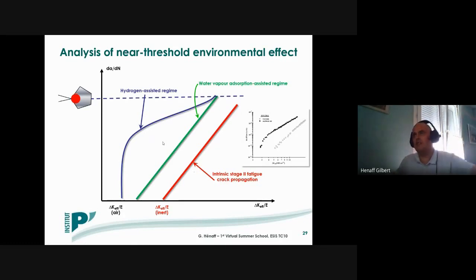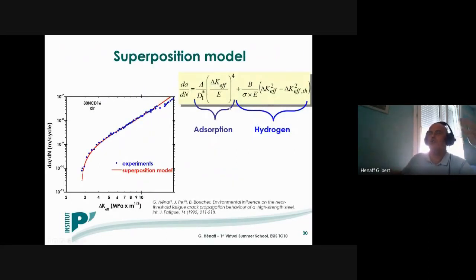And again, here I do not discuss the precise nature of this hydrogen-assisted regime. And just to finish, in order to describe the sequential effect of water vapor adsorption and then hydrogen assistance, we introduced this equation relating the fatigue crack growth rate to the effective delta K value with this superposition of the fourth power equation describing the adsorption, as I explained before, and here an empirical, I would say, equation taking into account the hydrogen effect. And by using this equation, we are able to nicely depict the near threshold behavior here in the case of a high-strength low-alloy steel.